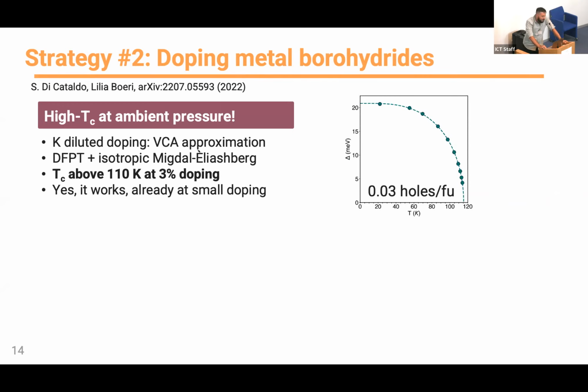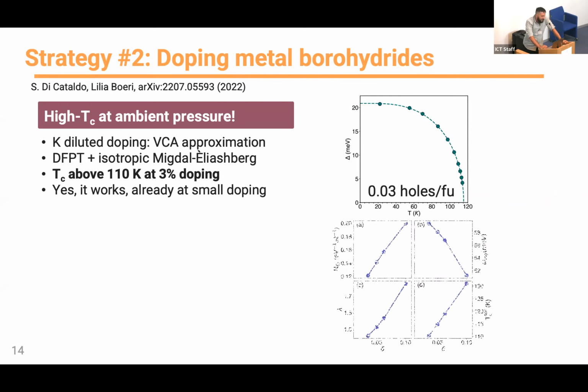So at small doping, we already have a very high TC. So we can follow the trend as a function of doping. And essentially what we learn is that indeed, as the doping increases, the density of states increases rapidly. But you can see that it's already quite large at this small doping fraction. The electron-phonon coupling average lambda is quite large, which ultimately leaves us with a high TC.